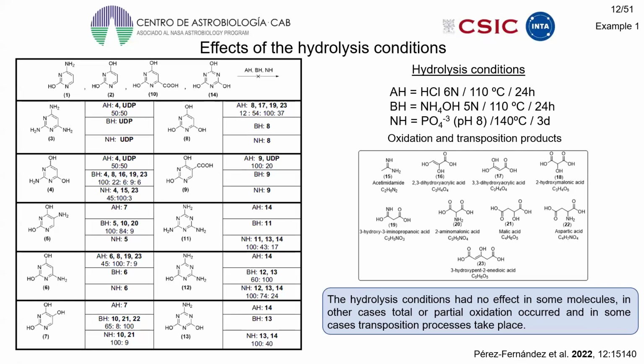So, in a second step, for the development of analytical methods for the identification of triazines and pyrimidines in hydrogen cyanide polymers, we explored the effect of several hydrolysis conditions on this series of compounds. You can see that some of them are not affected by any of the hydrolysis conditions assayed, but other ones are totally decomposed, and several transpositions were also observed. The hydrolysis conditions are especially interesting, taking into account the pH gradients present in natural hydrothermal systems, from pH 2 to pH 12. The hydrolysis conditions indicated along this talk can be considered as a faster transformation than in natural environments.